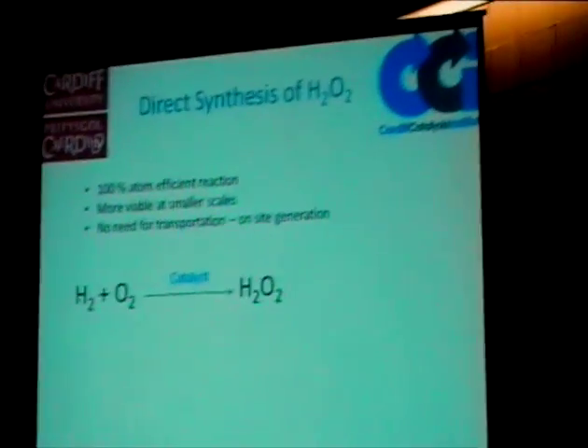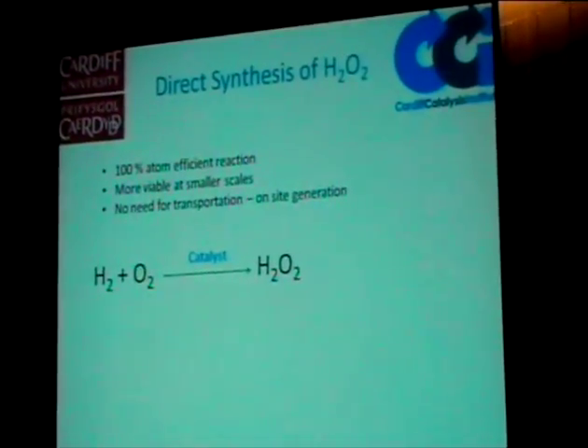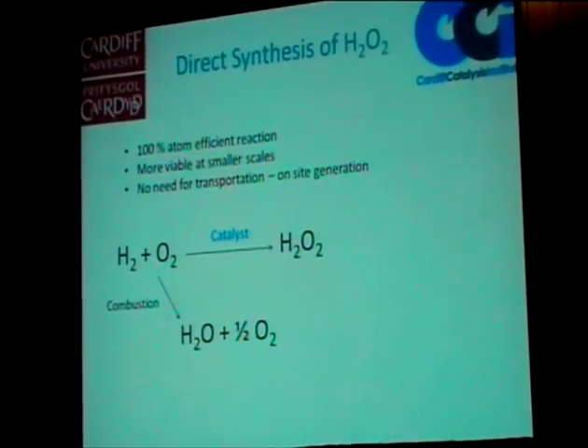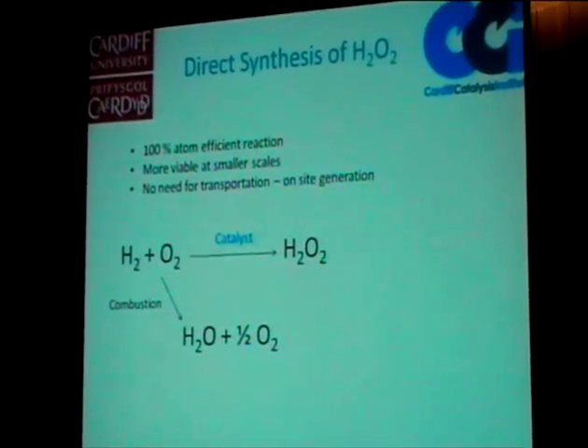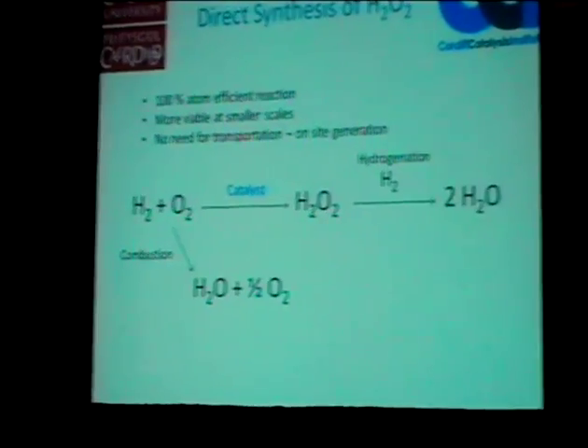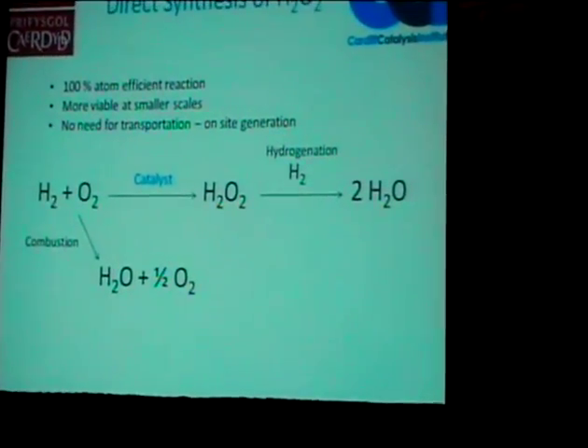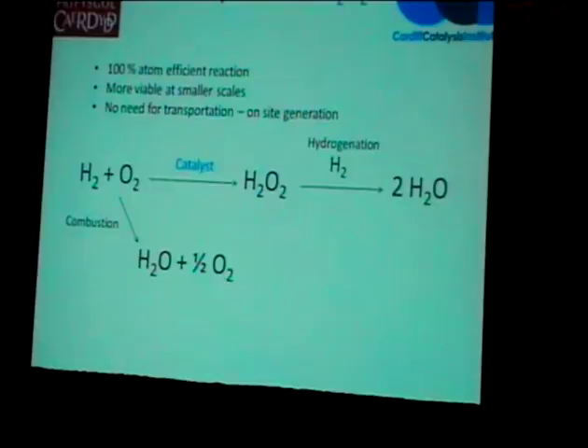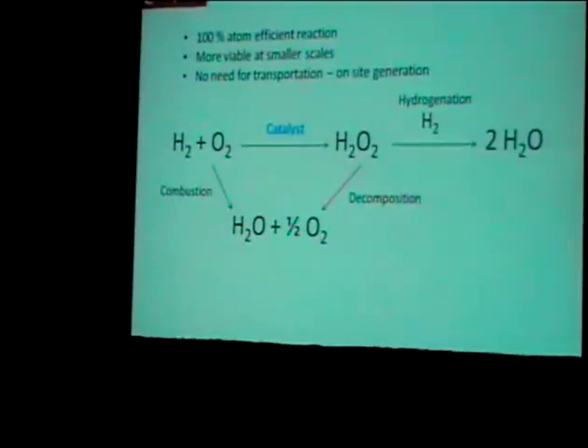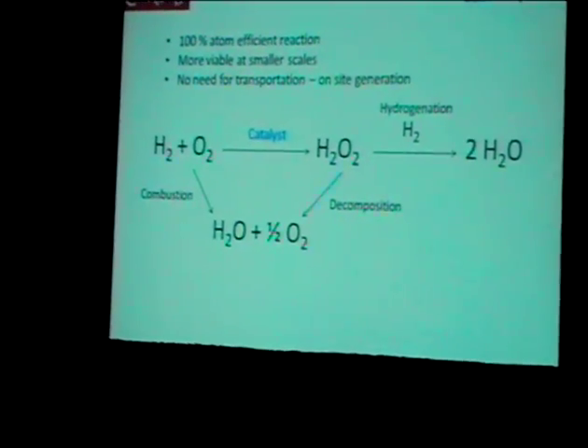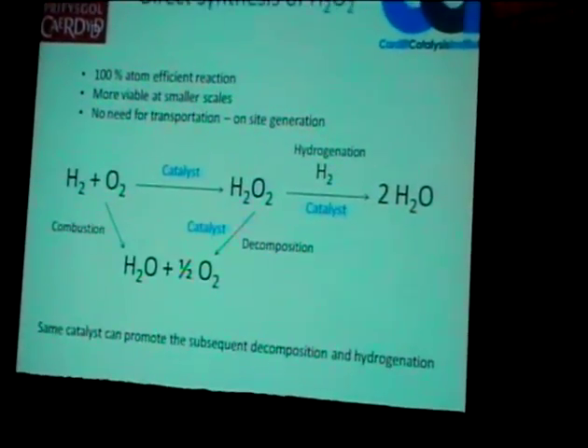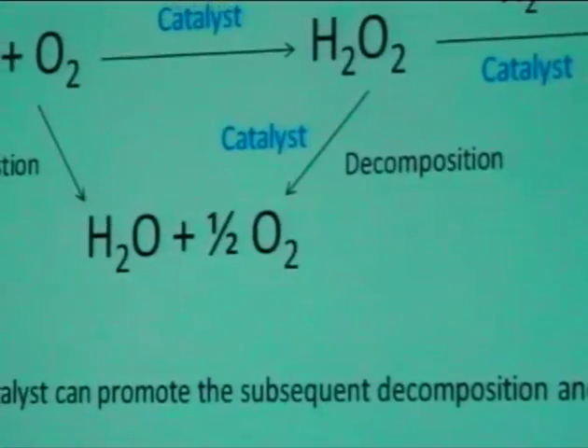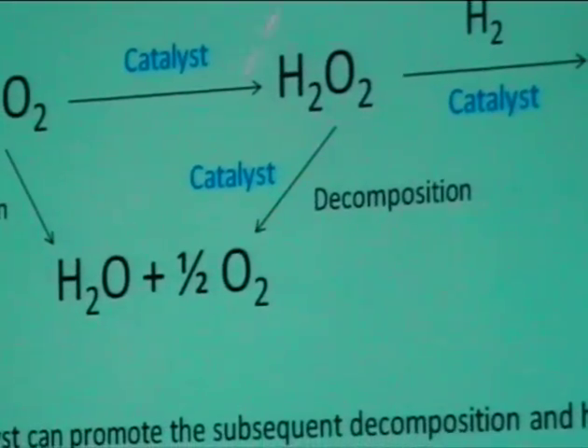The complications with this reaction are a number of side reactions. So hydrogen and oxygen can undergo combustion to form water. Hydrogen peroxide itself can be hydrogenated to water, and because hydrogen peroxide is not a particularly stable molecule, it can undergo decomposition to water, which all affect your selectivity. These two reactions can be substantially catalyzed by the same catalyst that can catalyze the synthesis of hydrogen peroxide. And the challenge is to stop the reaction here.